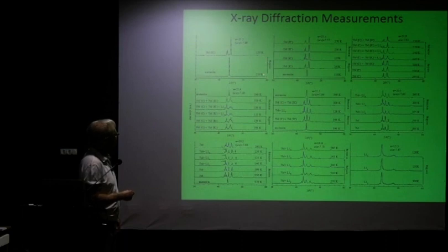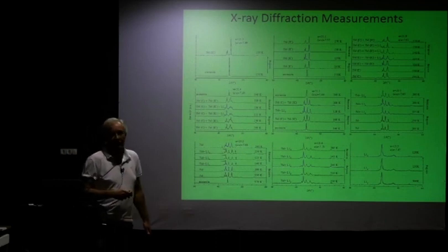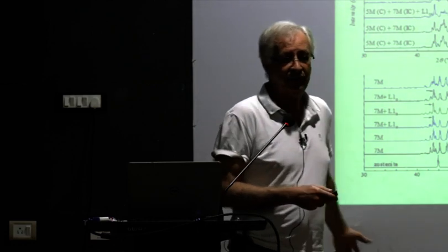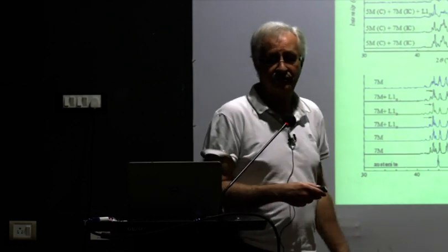Here on this sample, this was done on cooling. So what you see is you measure at 250 Kelvin. You see a structure that is related to the cubic structure, and you go down to 130 Kelvin, and you have something related to the Martensitic structure. But that's the only data you can take, because each of these data takes about 5 or 6 hours to take.